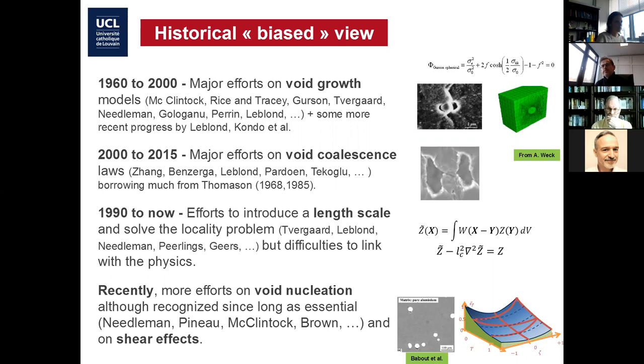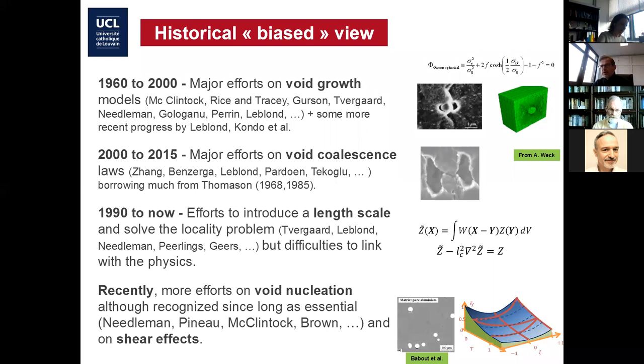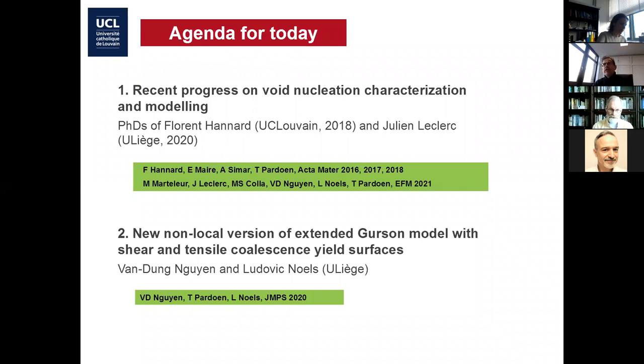When reviewing this history, you don't see much attention given to the first step: void nucleation. Since the beginning, people have known that voids nucleate on second-phase particles by fracture or decohesion, but there have not been many studies to really formulate physics-based nucleation models — they are essentially very simple models based on a critical stress or critical strain. Another subject that has not been sufficiently addressed, except in the last 10 years, is the role of shear effects in modeling ductile fracture.